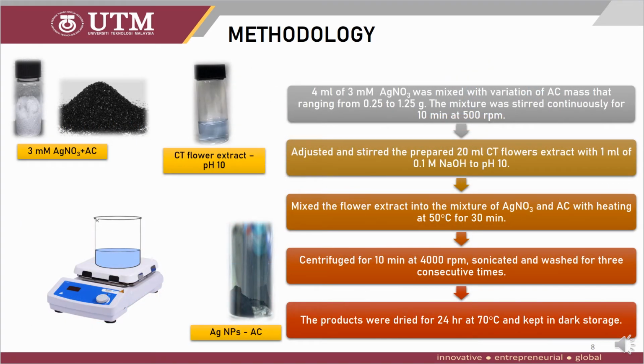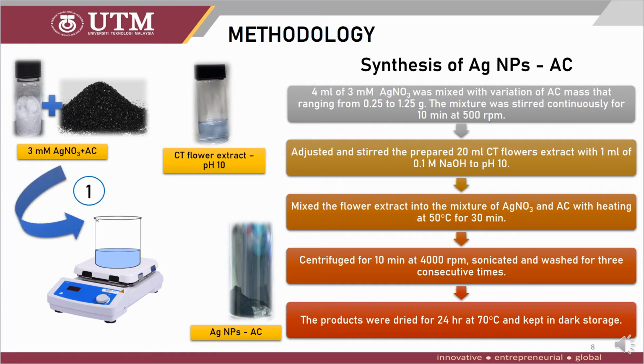So this is the methodology for the synthesis of Ag NPs-AC. First thing is to mix silver nitrate with mass variation of activated carbon ranging from 0.25 to 1.25 gram. After that, this mixture will be mixed with Clitoria (butterfly pea) flower extract at pH 10 for 30 minutes at 50 degrees C. After that, the mixture will be centrifuged, sonicated and also washed for about 3 consecutive times, and after that the final products were dried for about 24 hours at 70 degrees C and kept in dark storage.